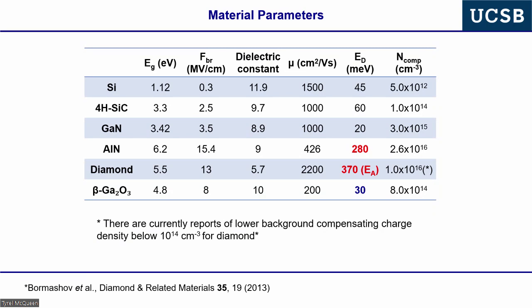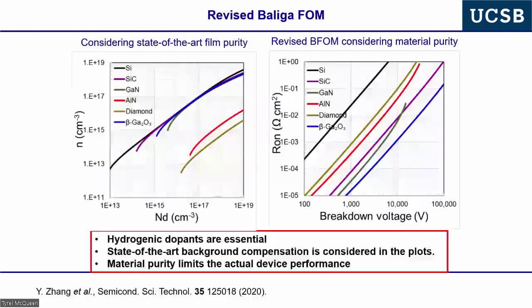We're very worried about the donor ionization energy, okay? And the beauty for gallium oxide is that we actually have hydrogenic dopants with ionization energies that follow almost exactly what's predicted from hydrogenic models of doping, okay? Aluminum nitride, which is a very hot topic right now, does not have hydrogenic dopants from any credible work. And in diamond, the shallowest dopants are not for the N-type material, they're actually for the P-type material, and the dopant ionization is about 370 meV, okay? Interesting is silicon carbide, it's not quite hydrogenic, okay? It's a little bit deep to be hydrogenic, okay?